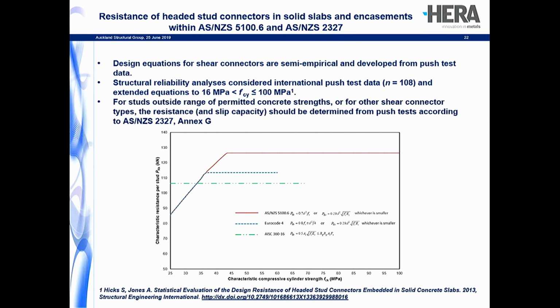The headline figures you can see from here are that the green line is the resistance from the AISC specification, up to the point where they have the cut-off in the compressive resistance of the concrete. The blue dotted one is Eurocode 4, and the red one is what's currently in 2327 and 5100 part 6. So you can see we really are mobilising the full capacity of the shear connectors from this reliability analysis. And the reason we were able to make that significant improvement was that in the reliability analysis we had much more test data available at our fingertips than either the AISC or the Eurocode 4 code writers had at the time when they were developing their rules.